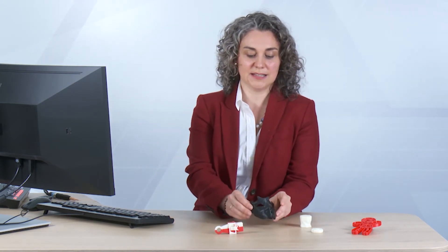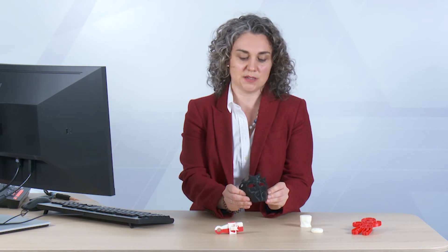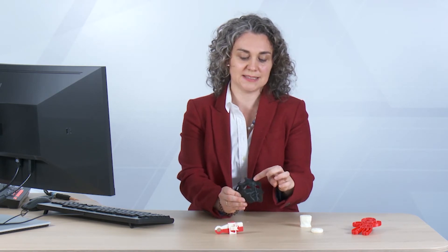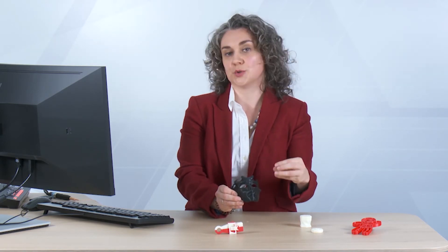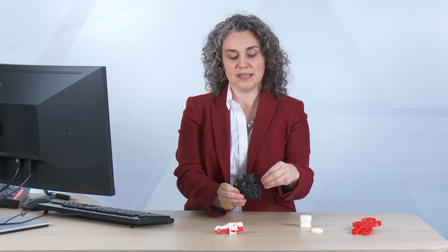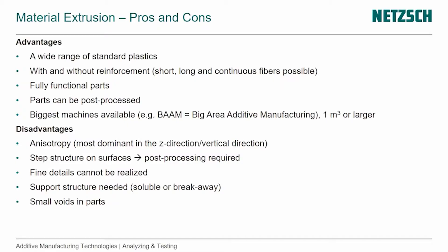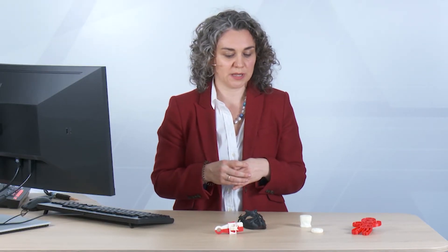Fine details cannot be realized. I have an example here of a little face mask printed during a student expo — it has details on top, but if those were any deeper, it would get really hard to produce them. Support structure is needed, though it can be soluble or break-away. And as you place bead next to bead, we get small voids in the parts, which is a problem for stress crack initiation and stress propagation.